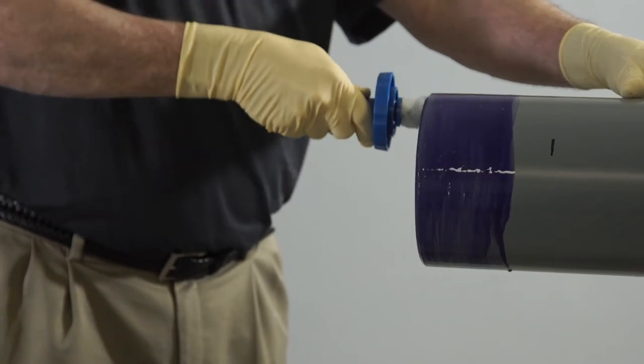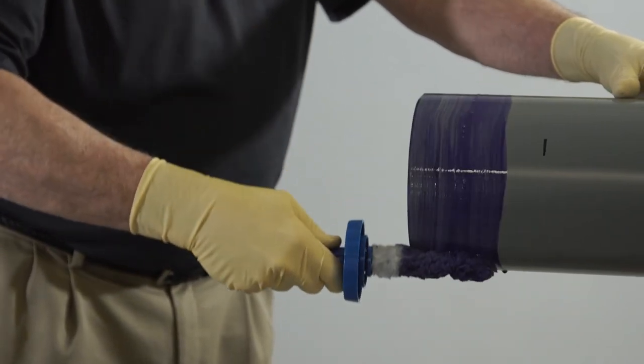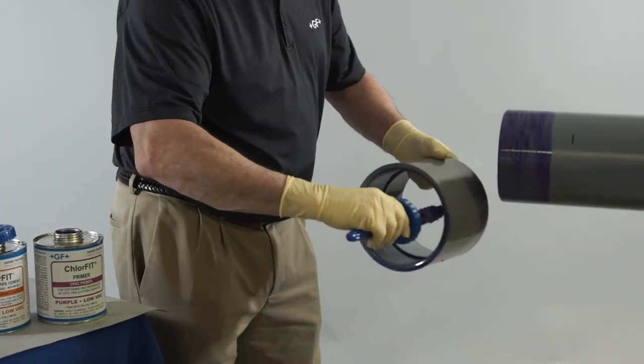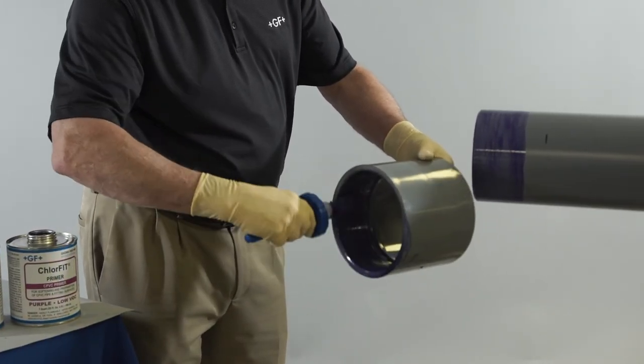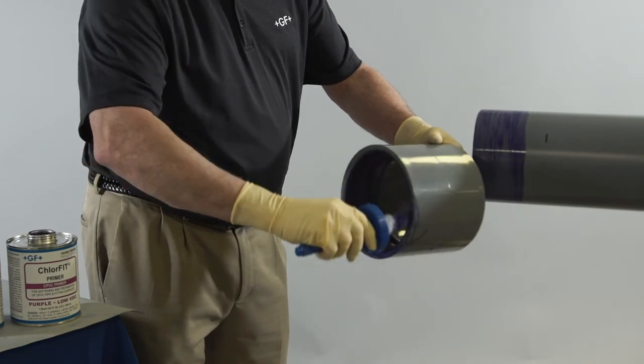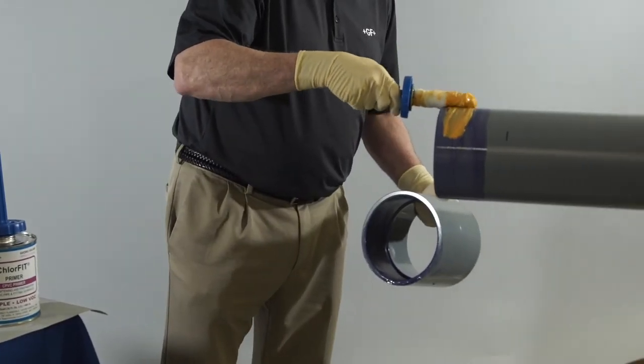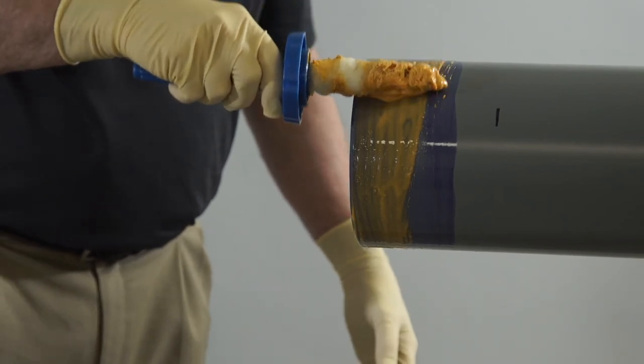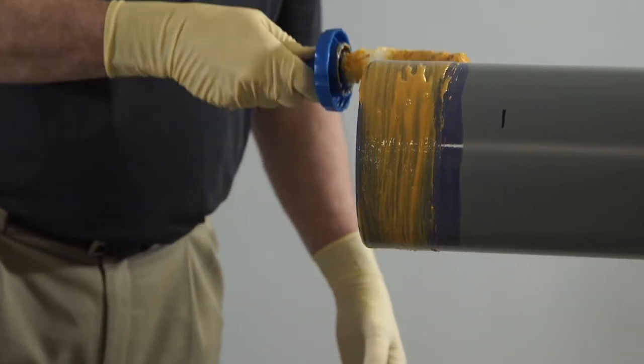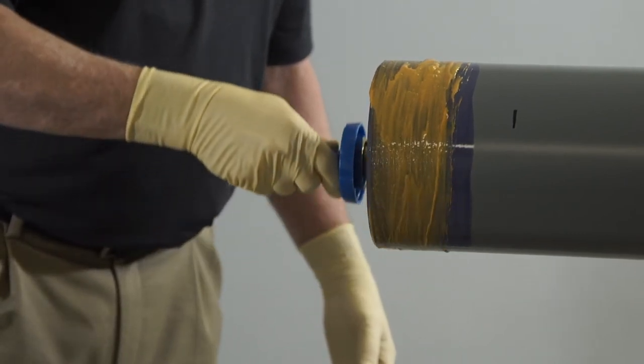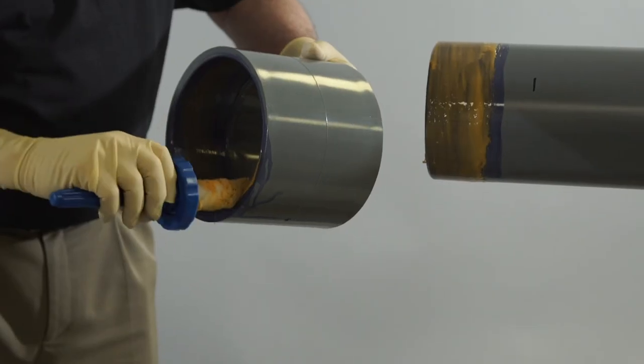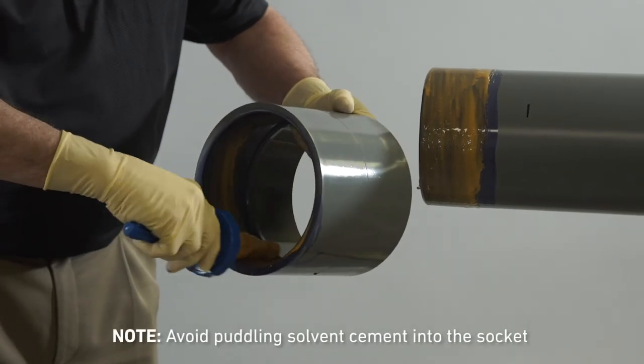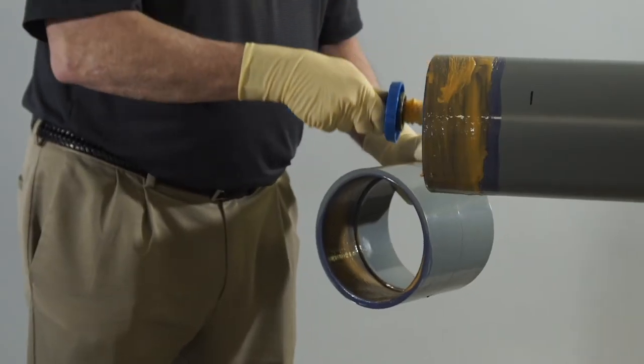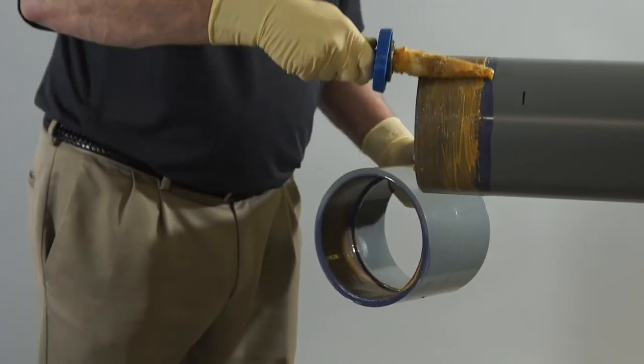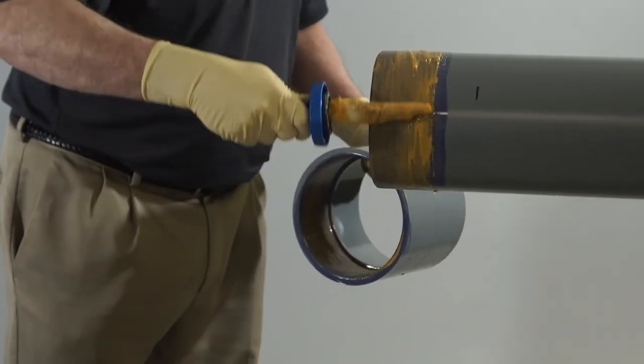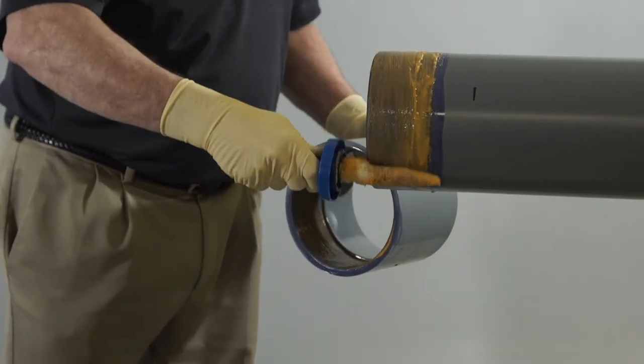Aggressively apply the primer to the end of the pipe to a point 1/2 inch beyond the depth of the fitting socket. Apply another coat of primer to the socket. Do not allow the primer to run down the inside of the fitting or puddle at the bottom of the pipe. Aggressively apply a full, even layer of solvent cement to the pipe, equal to the depth of the fitting socket. Do not brush the layer out to a thin paint type layer, as this will dry too quickly. Then, aggressively apply a medium layer of solvent cement into the fitting socket. Apply a second, full, even layer of the solvent cement on the pipe. Most joint failures are caused by insufficient application of solvent cement.